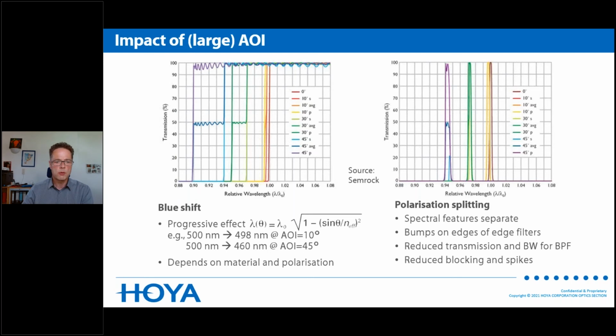And from the formula below, you can see that the blue shift is a progressive effect that really becomes severe beyond 10 degrees. For example, at 10 degrees, you only have 2 nanometer shift, but at 45 degrees, you already have a 40 nanometer shift. The shift itself depends on the material. It is tied to the effective refractive index, and it also depends on the polarization. You can see that for large angles of incidence, the P and S polarizations have different blue shifts.